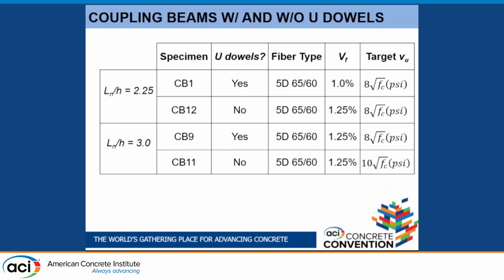So I'm focusing on these 4 coupling beams, 2 aspect ratios, 2.25 and 3. For each aspect ratio, I'm looking at without dowels and with dowels. Target shear stress, in most cases, 8 root of f prime c. In one of the coupling beams, we have 10 root of f prime c. And volume fraction, 3 out of 4 at 1.25% versus 1%.